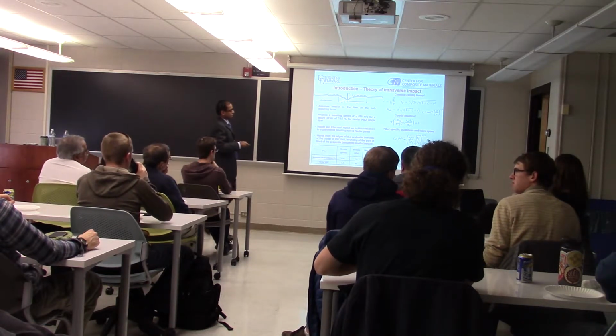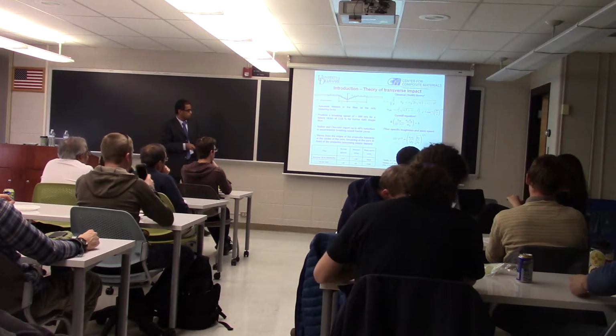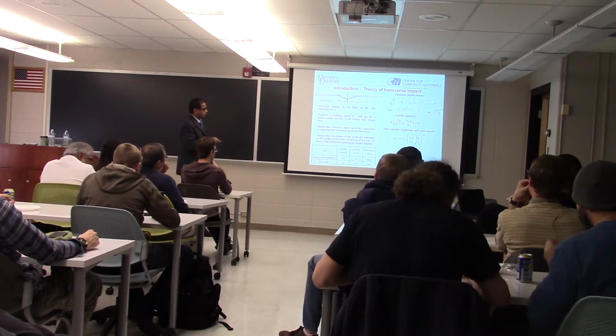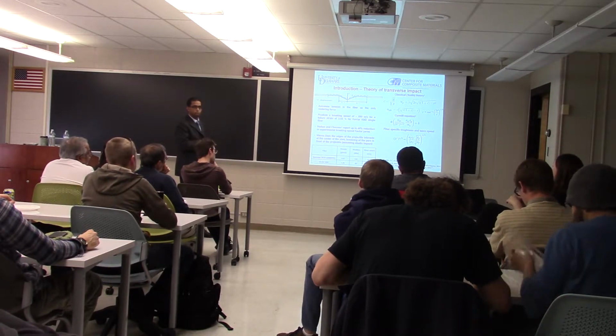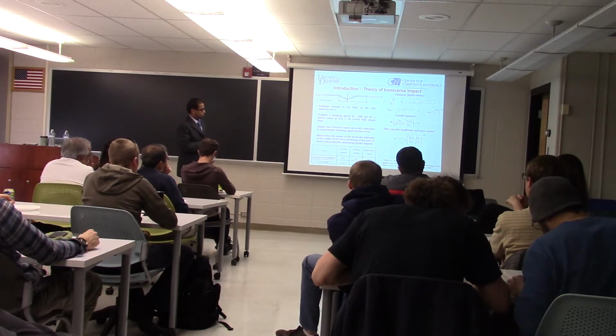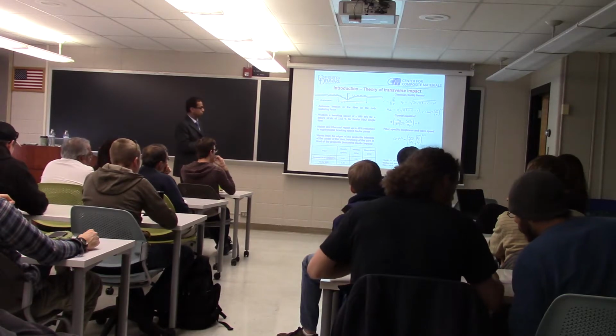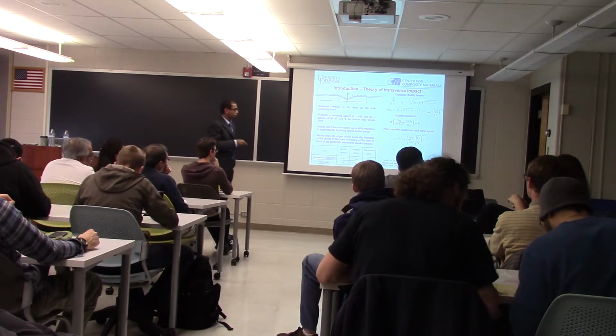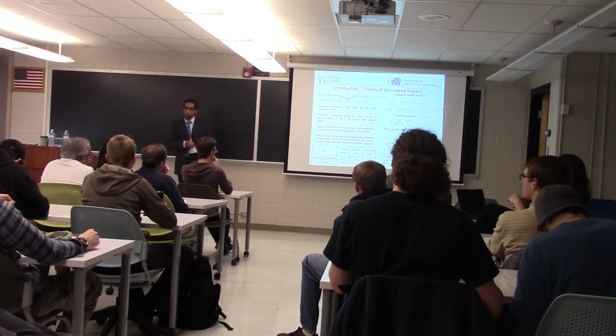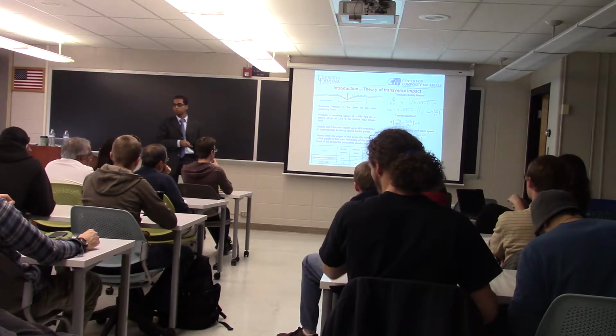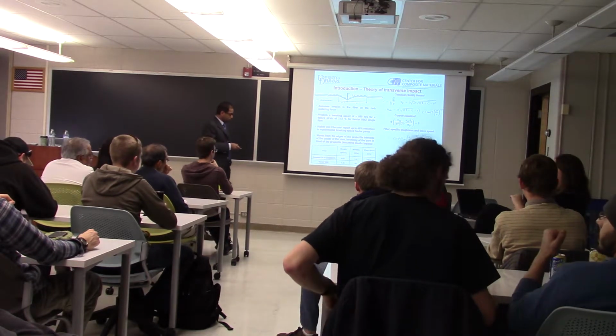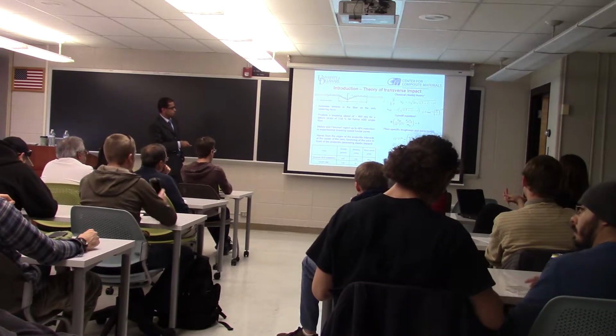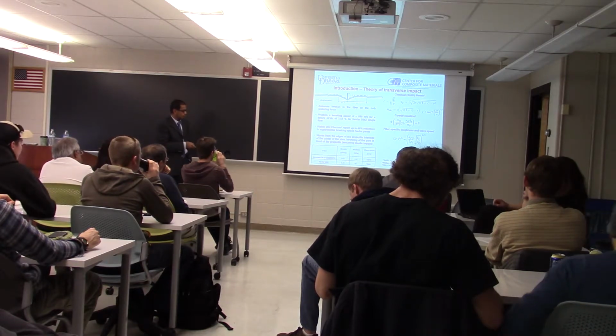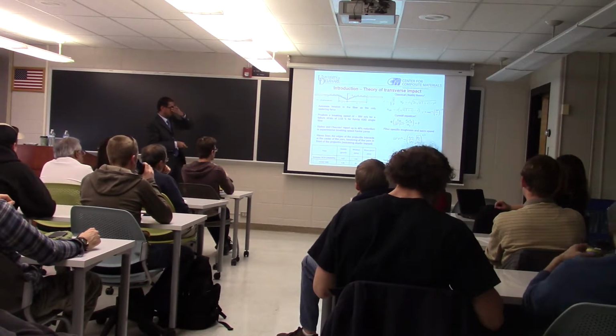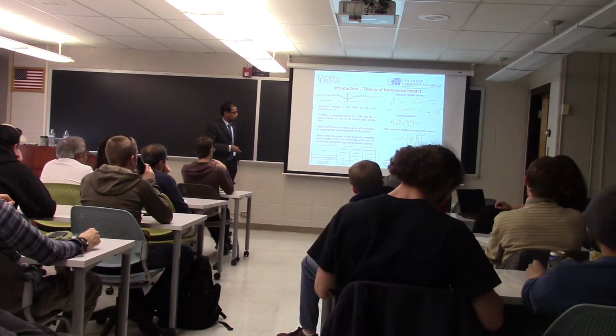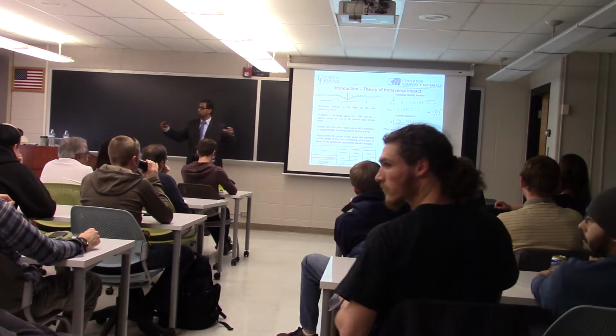Then if we think about what properties affect this ballistic performance, Cunniff showed empirically that this V50 linearly scales with what's called the Cunniff velocity, which is a product of the fiber specific toughness and the fiber longitudinal wave speed. This velocity has been shown to be useful in initial relative ranking of ballistic fibers, except in the case of polyethylene fibers, arguably due to its low melting temperature. Here I give some examples, if you are interested in numbers, of these wave speeds. Polyethylene fiber has a wave speed just over 10,000 meters per second, whereas Kevlar has just over 7,500 meters per second. This is the speed at which the impact energy is taken away from the impact location.